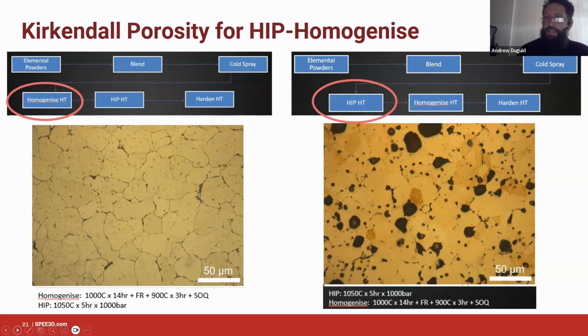It's full of porosity. So this is the dreaded Kirkendall porosity that we alluded to before. What we're seeing there is that we've done the HIP process, and it would seem like we've got a fairly good degree of bonding in the material as a result of the HIP. The microstructure, obviously, key point here, looks nothing like a cold spray microstructure anymore. So that's all well and good. But what we realized after we dug into it is that the HIP cycle is nowhere near long enough or aggressive enough to completely homogenize the aluminium and the iron and the nickel, for that matter, or the iron particularly.